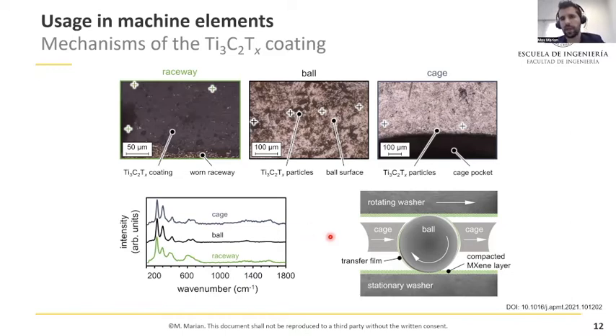So basically, the mechanism we came up with is that we have a compacted MXene layer on the raceway, which is the primary and highest loaded contact of this rolling bearing, which gets compacted due to constant overrolling, but we also get a kind of transfer to secondary contacts of the rolling bearing, for example, the contact between the ball and the cage. And since we know that the cage is a main cause of bearing failure under these operating conditions, one can imagine that this is, of course, quite beneficial to extend the service life of the bearings.